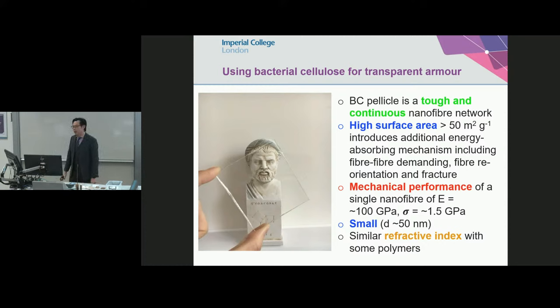If you think a little bit about it, this bacterial cellulose is itself a tough, continuous nanofibrous network. When you dry it out, it has a rather high surface area. That 50 square meters per gram is actually our lower bound. When you impregnate the whole network with a resin, as the fiber deforms, you have a lot of surface area that the crack has to go around. That, technically speaking, increases energy absorption mechanisms such as fiber debonding and so on. That should work. And ultimately, the single fibers themselves have to break, and they are quite strong and quite stiff as well. So that actually helps.